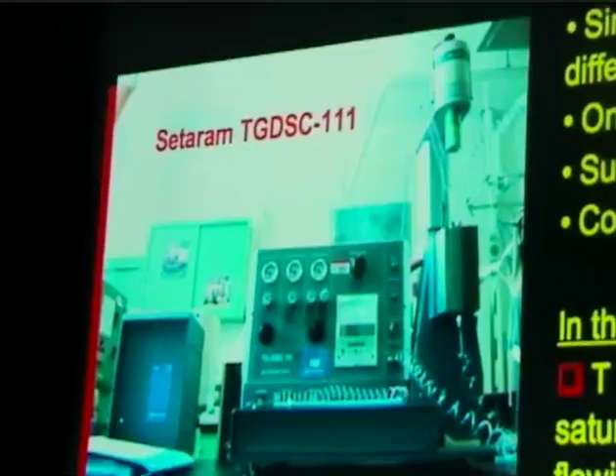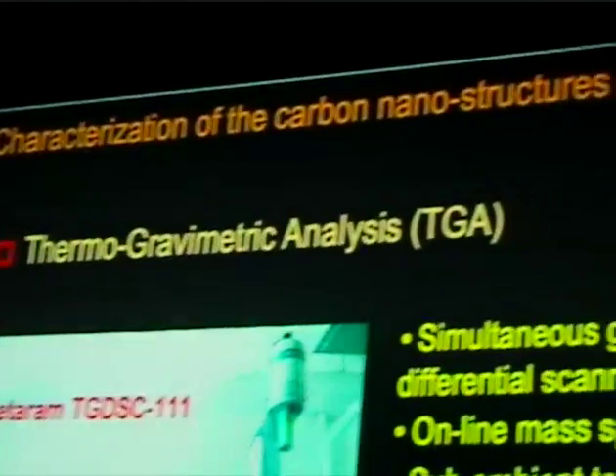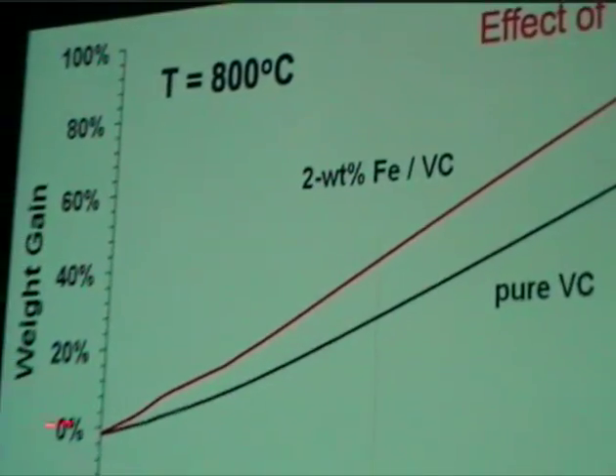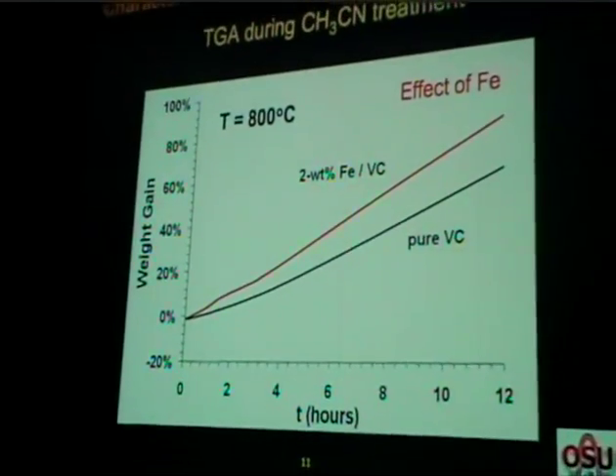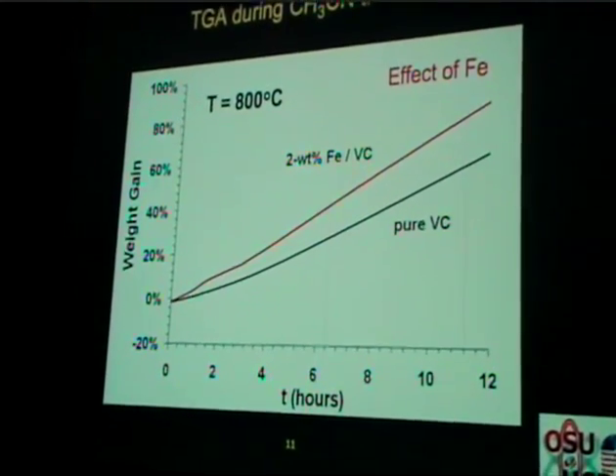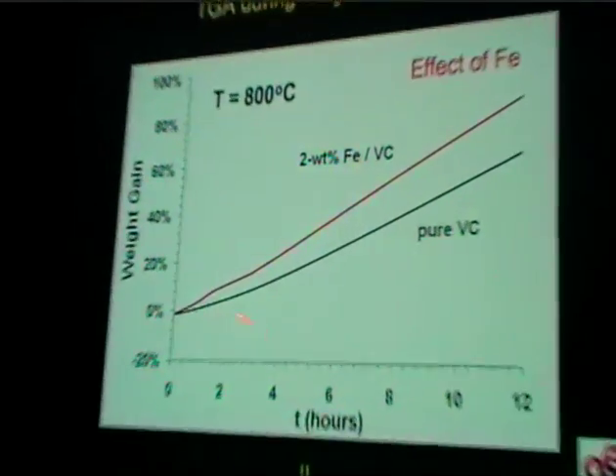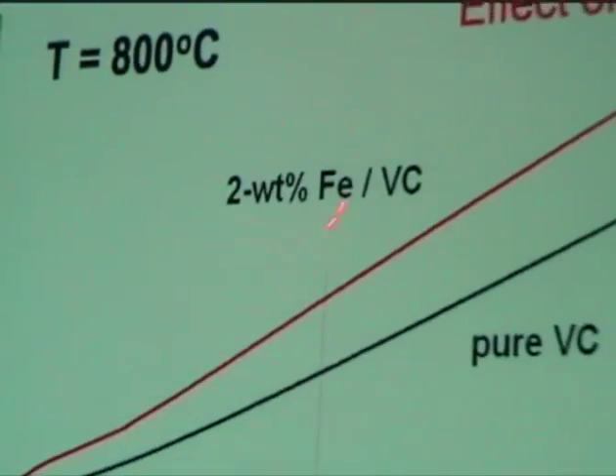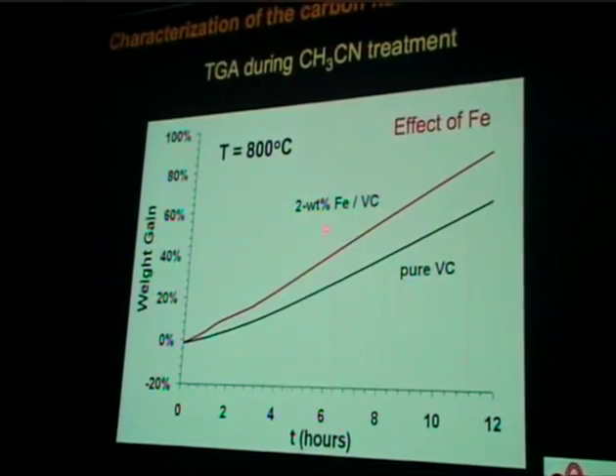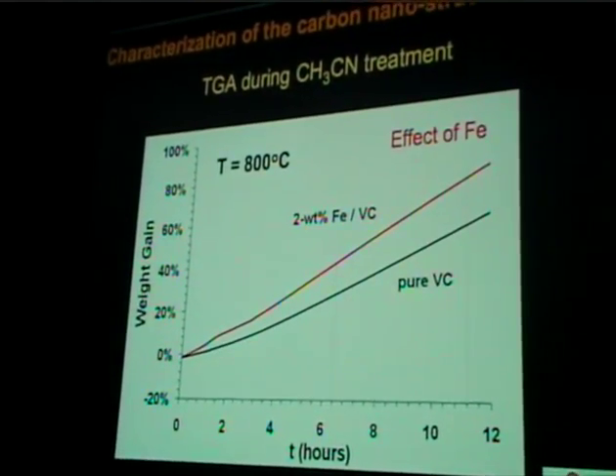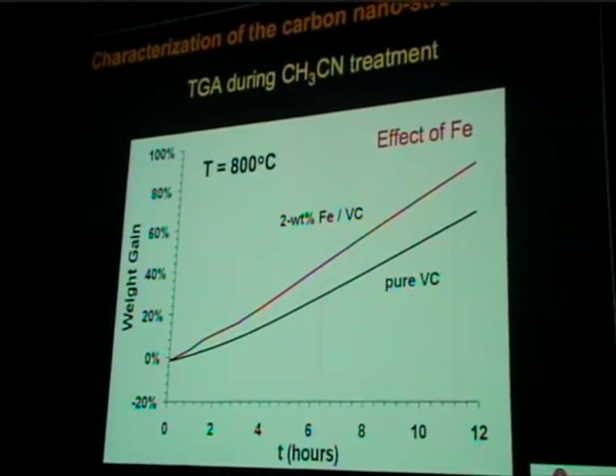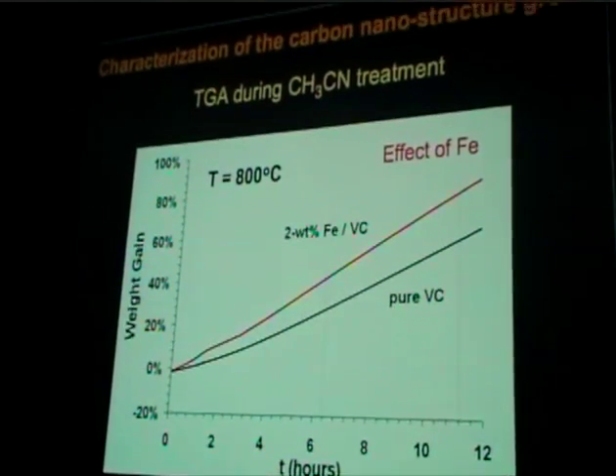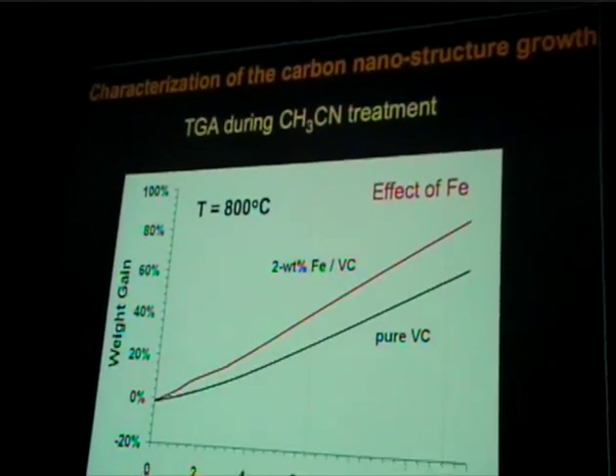Now, if we look at the carbon deposition process using thermogravimetric analysis, what we see is that if we look at the weight gain, and weight gain really represents the carbon deposition on the surface, when we have Vulcan carbon doped with iron, there's a faster weight gain. So we have more carbon deposition, carbon nanostructure growth on the support materials.